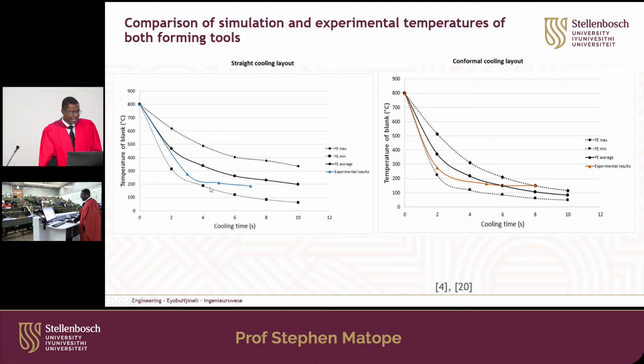So in this case, for the conventional, after about 7 seconds, that's where we were reaching the required 200 mark. But in the conformal cooling, which produced the conformal cooled tool, we find that we are reaching that 200 degrees Celsius already below that. In 5 seconds, we are really way down. Actually, just before 4 seconds, you're already reaching the required temperature.